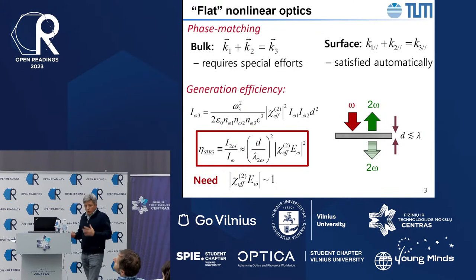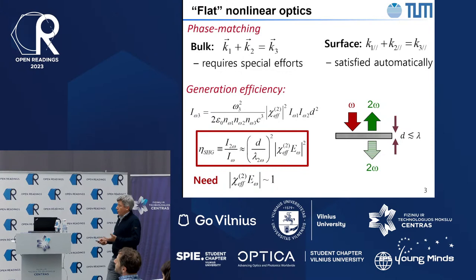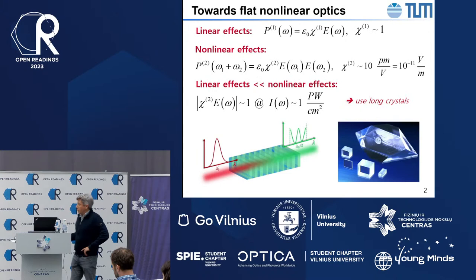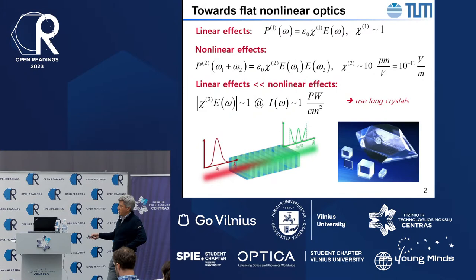Now, what would flat nonlinear optics give us? So first of all, maybe I'll go back for a second, when people use nonlinear optics, they rely on this relatively weak nonlinear polarization, and then they use bulk nonlinear crystals that span many wavelengths of light to slowly build up the effect of this nonlinear polarization into a sufficiently strong output beam at, let's say, some difference frequency. So these nonlinear crystals are long.